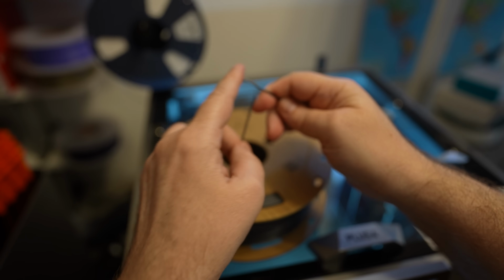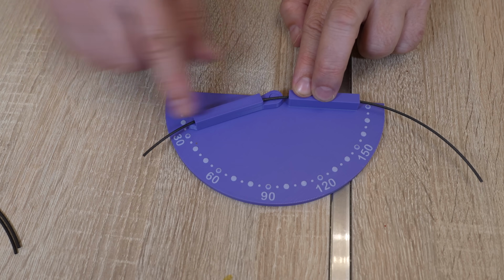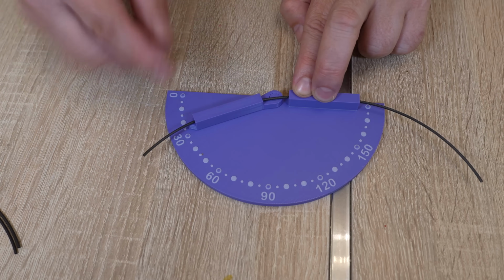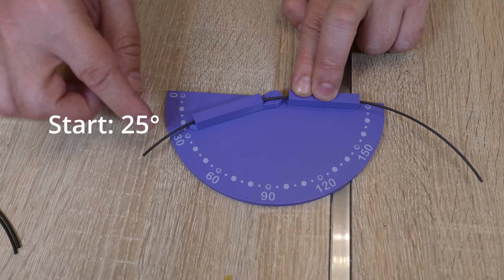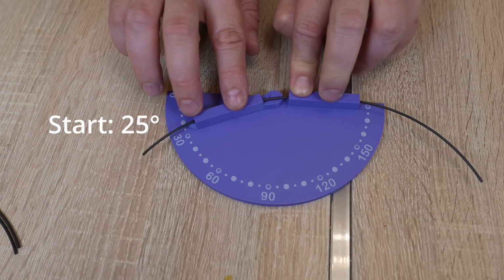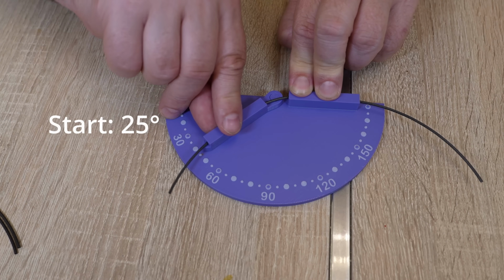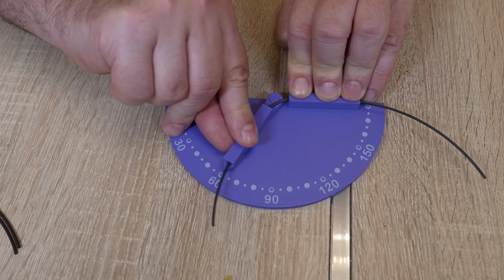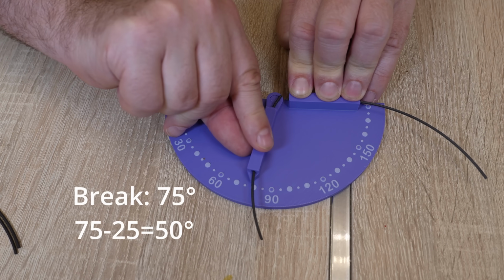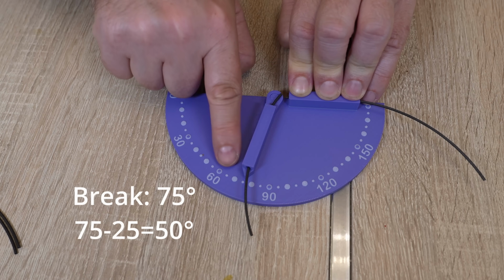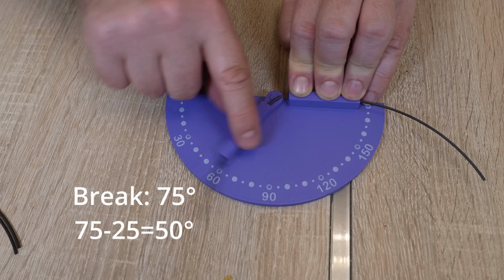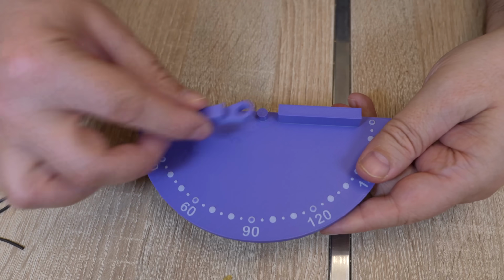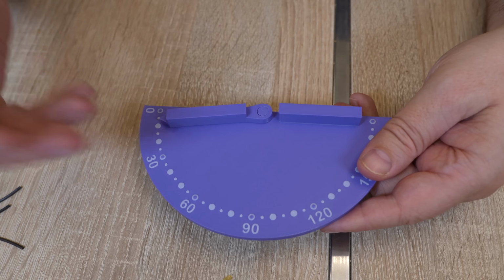Quite brittle filament. In the meantime, I made this tool. With this I can measure this bending more accurately. Yes, it has some curve and start angle, but let's try to measure when it will break. Approximately 75 degrees. You can download this from Printables if you want to check your filament.